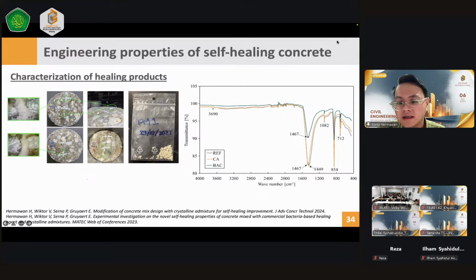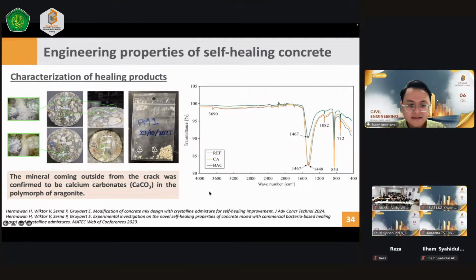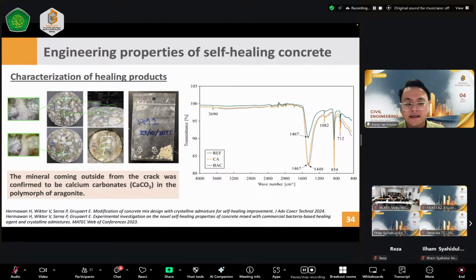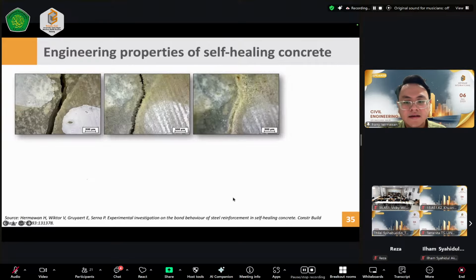If you see the picture on the right hand side, there are some intense peaks at, let's say, 3690, 1467, 1082, and these peaks, regarding the wave number, are related to the mineral type, or what kind of mineral is forming from the cracks. And from my study, I can confirm that this mineral was calcium carbonate in the polymorph of aragonite.